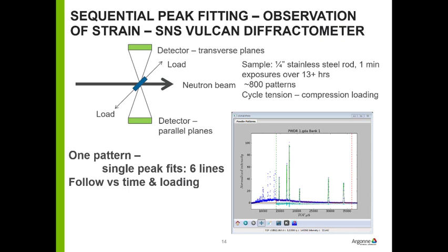Well, one thing is that systematic errors will make it really hard. If you've got a sample displacement error that shifts the pattern in some way, that makes it much more difficult to do the indexing if the peaks are just not in the right place. If it's a pseudo-symmetry situation where two of the lattice parameters are very similar, so you don't get a clear separation between the peaks, that's hard to index.